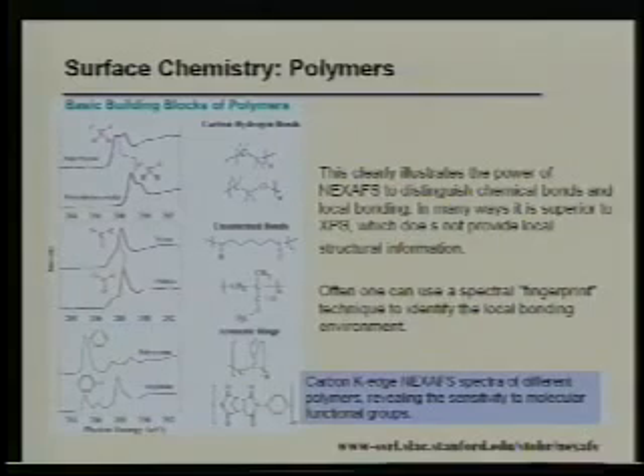The next thing that's of interest in these materials is you can actually get surface chemistry or chemical information from your NEXAFS. And what I've shown here is for a polymer system. And the first two plots, we see that this is a carbon X-ray absorption edge, and we see if we have a polystyrene and a polyethylene, you can see that if you have a carbon bonded to oxygen or carbon bonded to hydrogen, these edges shift. And again, if you have a double bond, you have now pi star features.